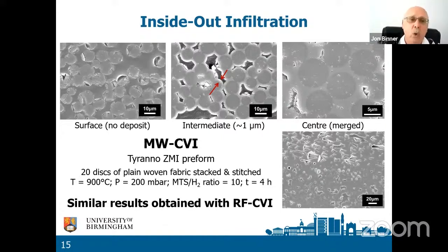And if we then have a look at the surface of the composite, we have no deposit. That matrix you can see there isn't a matrix. In fact, it's just resin holding the fibers together while we polish the surface. But at the center, we've now got more or less complete deposition. So now you can see the circular fibers, and then all around them is silicon carbide. So at the center, after just 4 hours, the sample is fully cooked.